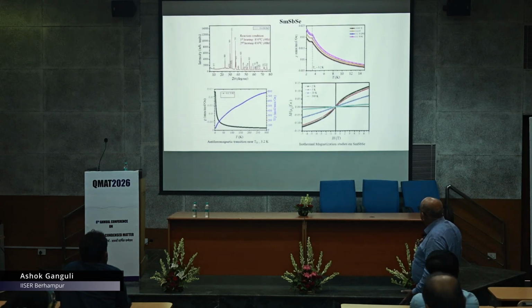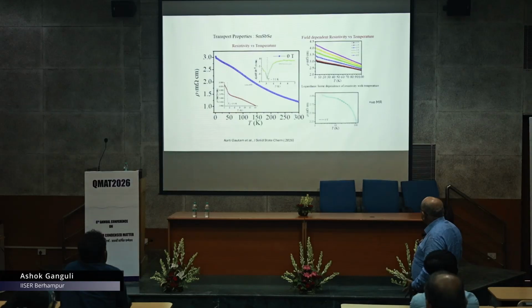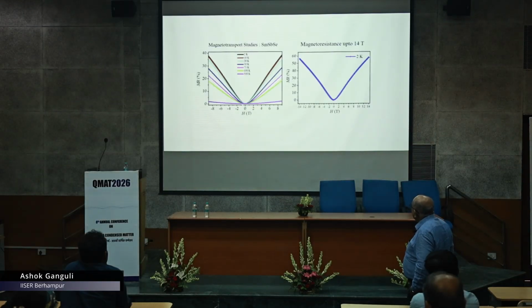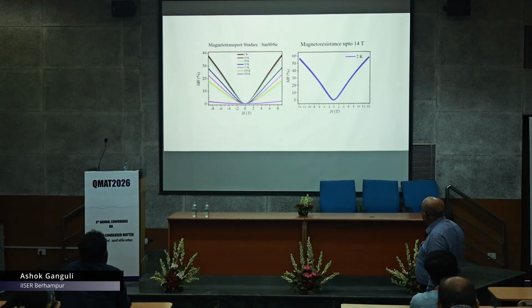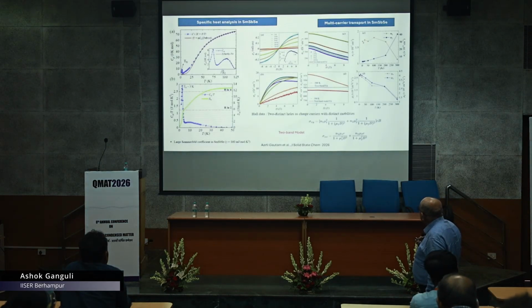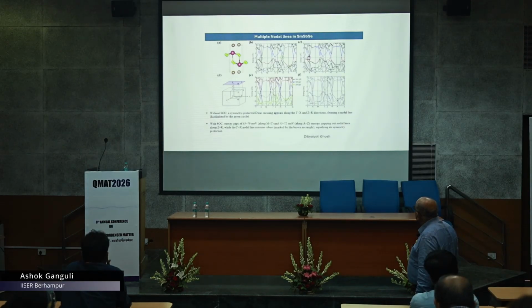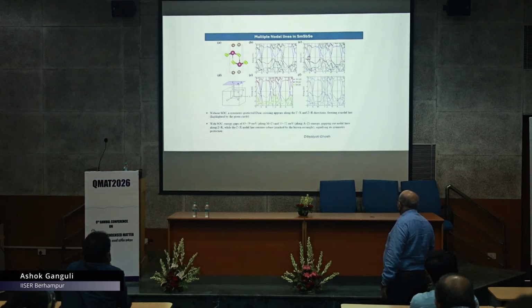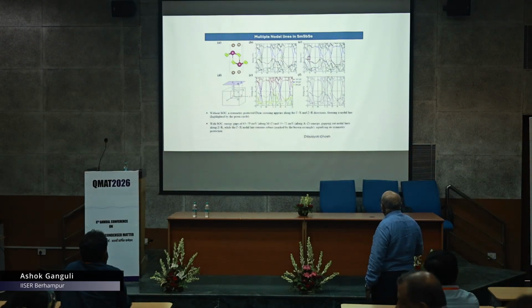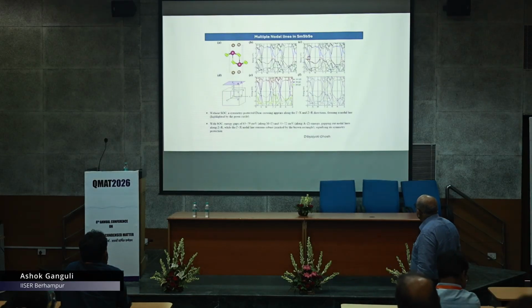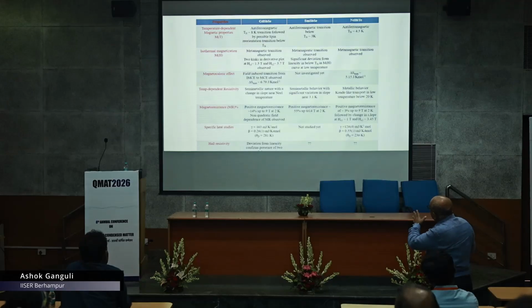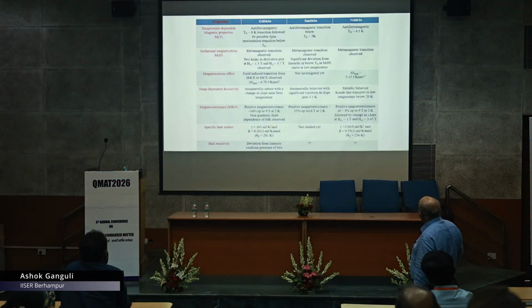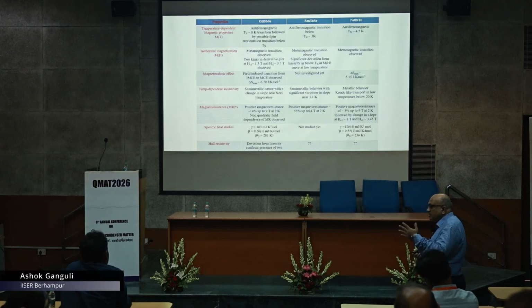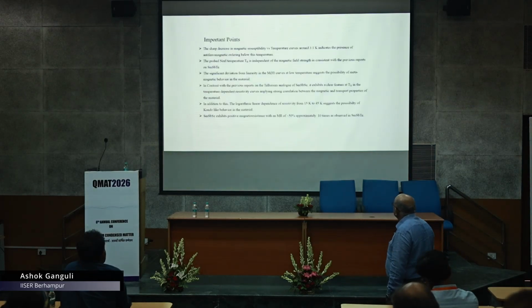So I will quickly skip. Samarium antimony selenide has similar properties. We have done all kinds of measurements. You can look at the linearity of the magnetoresistance up to 14 Tesla. For SmSbSe, we similarly have a very large Sommerfeld coefficient, and again a multiband nature in the plots. Here you can see the states at the Fermi level, which are contributed by selenium, and other features are there. This is a comparison of these three compounds: antiferromagnetic, metamagnetism, and some Kondo type behavior that you can get from the resistivity plots.